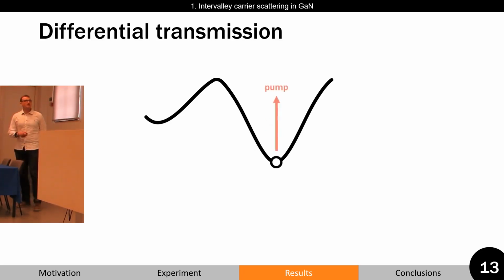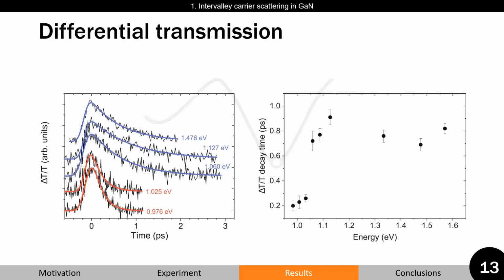In case pump energy exceeds intervalley energy, due to carrier scattering, transients are expected to slow down. This is indeed what we observed in the experiment. With increased pump energy, decay times slow down. By plotting decay times versus pump energy, threshold-like behavior is observed.